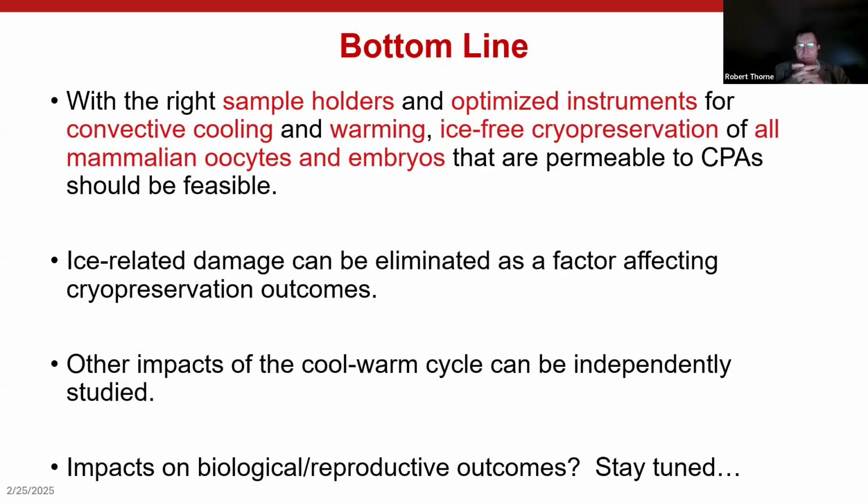Yeah, so absolutely. The reasons not to, I mean, that's what cryo-EM does. They use ethane actually, and they'd really like not to have to use ethane because it's flammable. You've got to condense it for each experiment. Their health and safety officers aren't wild about having grad students working around it. But that said, if you really want to push cooling rates to the limit, you're going to want to use ethane or propane.